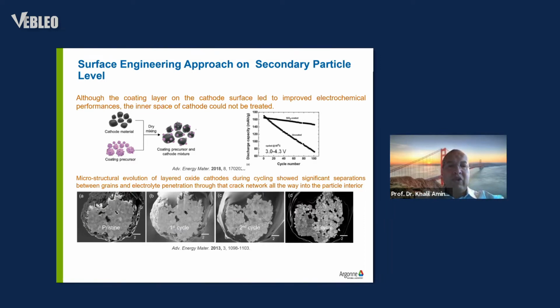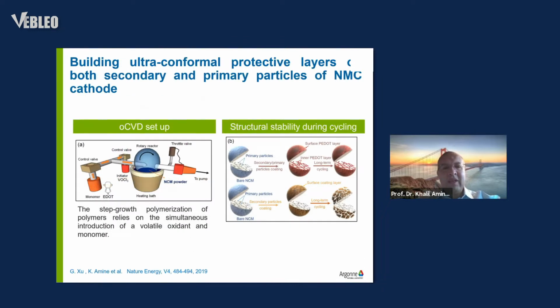So as I say, at Argonne, we developed a very unique coating technology. It's based on a gas phase polymerization to form a polymer, a PEDOT polymer, that is both ionically and electronically conductive. So you get some ionic conductivity to allow lithium to move in and out of the grain boundaries or inside the particles, and you have electronic conductivity to enhance the overall conductivity of the material. So we take EDOT, which is a gas, and vanadium oxychloride, an initiator, which is also a gas. Gas goes everywhere. It penetrates the particles, and then you heat it up at 100 degrees C in a rotary reactor, and you form a PEDOT polymer that basically creates a uniform coating across the particle inside and outside.